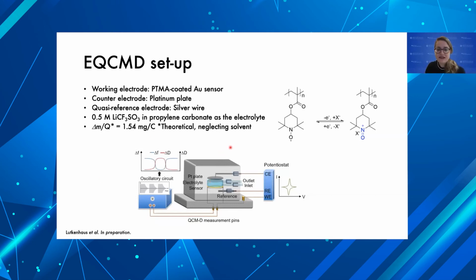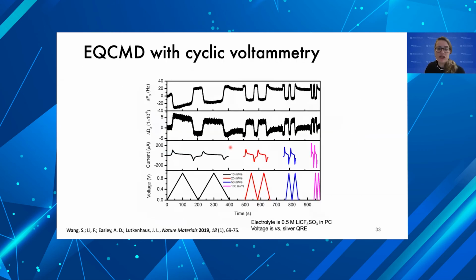So anyway, this is our setup, and we're going to be doing cyclic voltammetry. What we do is input a triangular voltage wave of different scan rates: 10, 25, 50, and 100 millivolts per second. The output from our potentiostat is the current. So these two together give you your cyclic voltammogram. We've just plotted it in the time domain. And then the raw data from the QCMD is plotted up here, where we observe the changes in frequency and dissipation. What you'll note is right when we have a redox peak here and here, we have step changes in frequency and dissipation associated with oxidation and reduction.